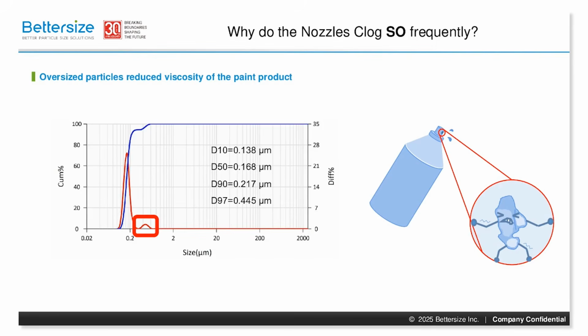In this real-world case from a leading paint provider, the nozzles of canned paint clogged abnormally often. The culprit was identified using the Bettersize 2600: oversized particles. This distribution curve reveals those oversized particles, the peak highlighted with the red box, even when most particles are in the right size. These oversized particles can disrupt the optimal packing of smaller particles, reducing overall viscosity and leading to inconsistent flow and clogging.